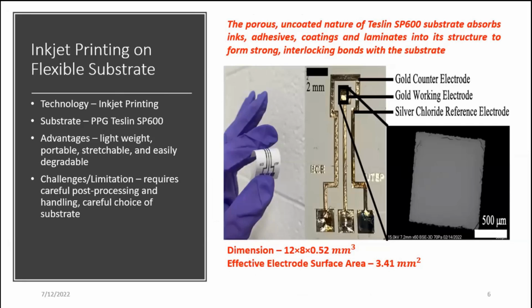Now, the technology is the same, that is inkjet printing, and for substrate we have chosen Teslin, which is PPG SP600. The reason for choosing the substrate is it has a porous and uncoated nature, which allows it to absorb maximum silver nanoparticle ink inside it, so that it can bond very strongly with the substrate, which increases the adhesion of the printed sensor. Because what happens to flexible sensors is they have really less adhesion, and when we are doing some electrochemical analysis, we just actually break or damage the electrode in the process.